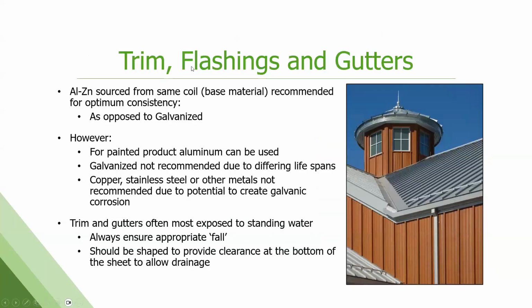Again, your trims, flashing, and gutters should be as close to the same metal, if not the same type of metal, as the panels that you're using. So yeah, aluminum is a good choice, right? But copper and stainless, other metals, we really just don't recommend them because of that potential for galvanic corrosion. And then, of course, gutters and trims, make sure you don't have standing water and that they're shaped so that you can clear out the bottom on a regular basis.